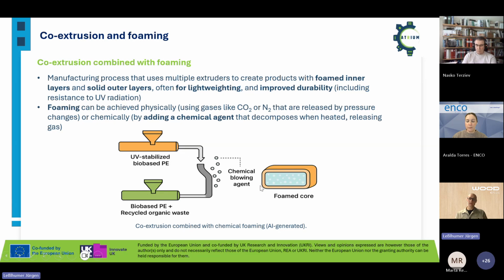And here you can see a picture of the process we use in the project. In the core layer, we have bio-based polyethylene, and we combine this with recycled organic waste. The shell layer is a UV stabilized bio-based polyethylene. And this is the end product: the foamed core layer protected with a UV stabilized shell layer.